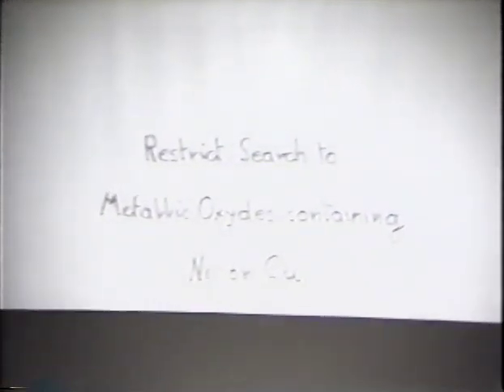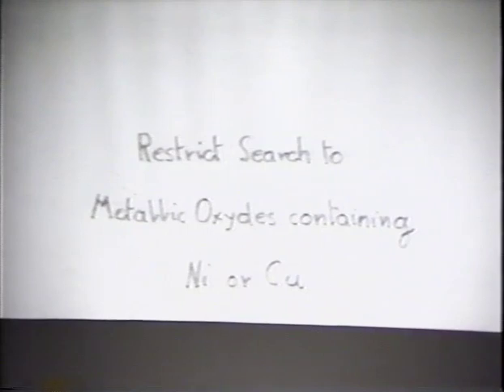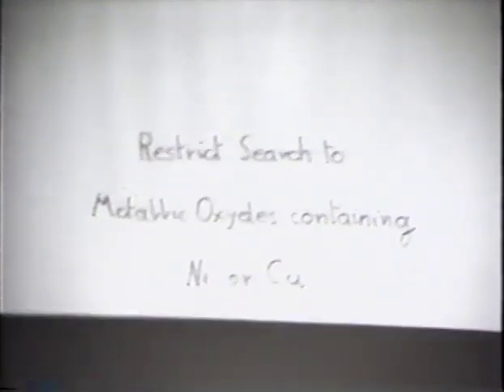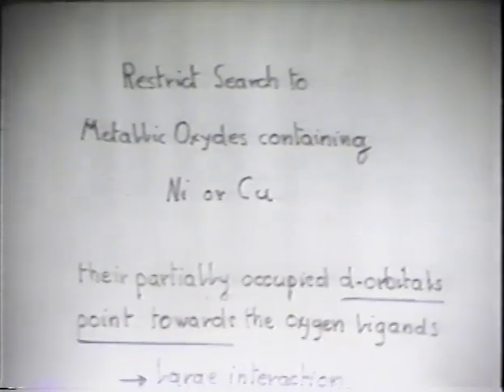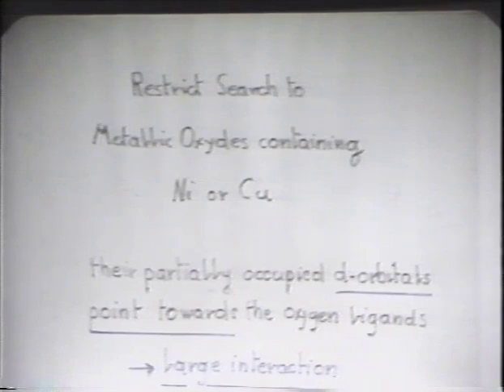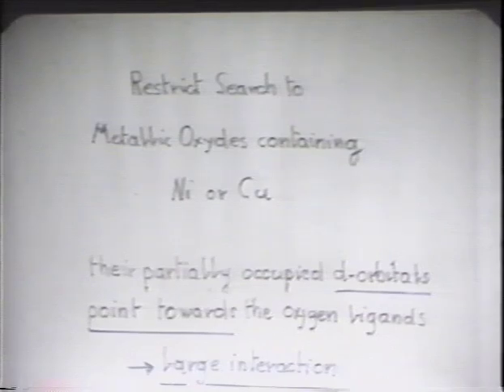The other part of the concept was to restrict our search strictly to metallic oxides containing nickel and copper only in octahedral coordination. Why? Because they have partially occupied d orbitals which point toward the oxygen ligands. And therefore, this was our view: one would have a large interaction between the metal and the ligand. You see here the octahedron and a copper inside.